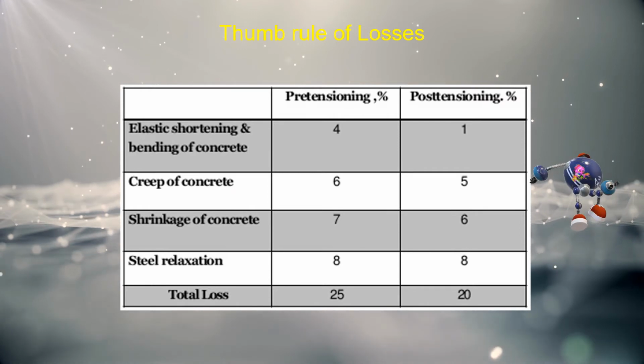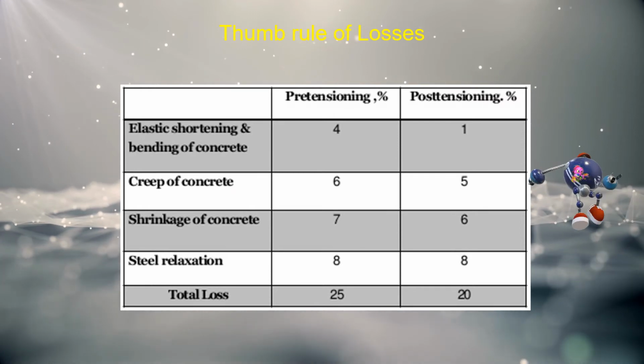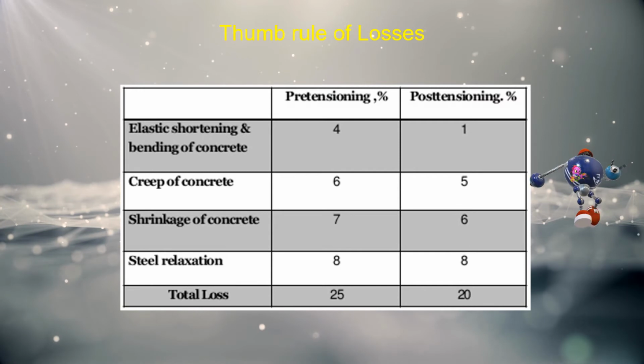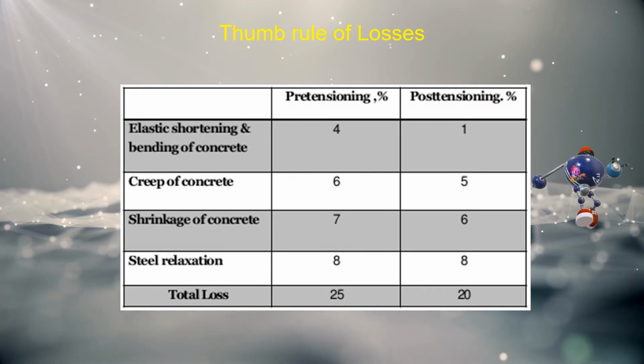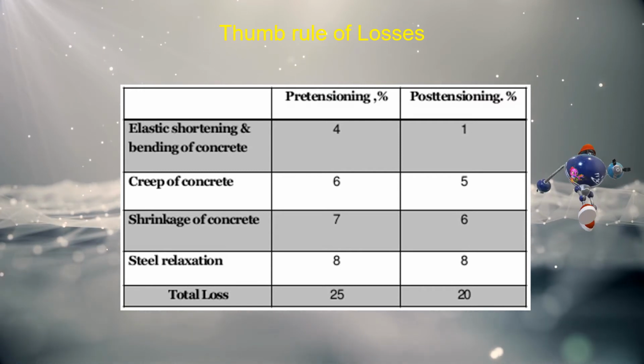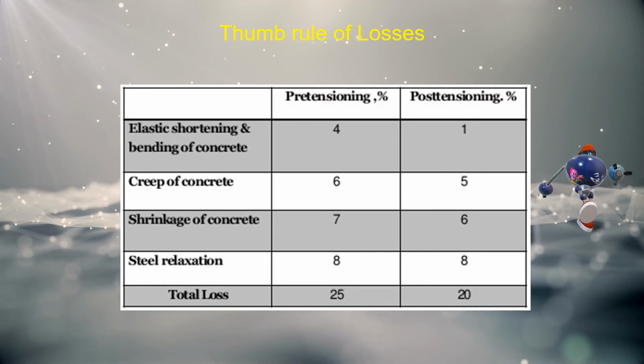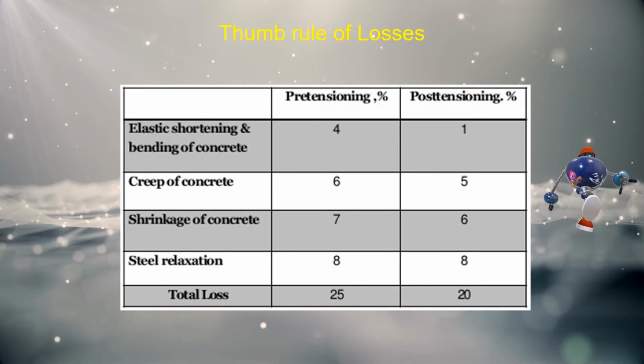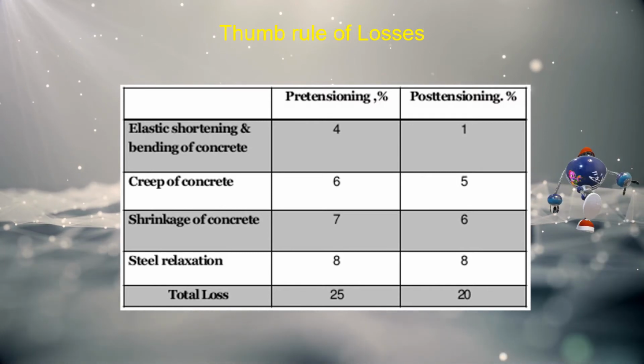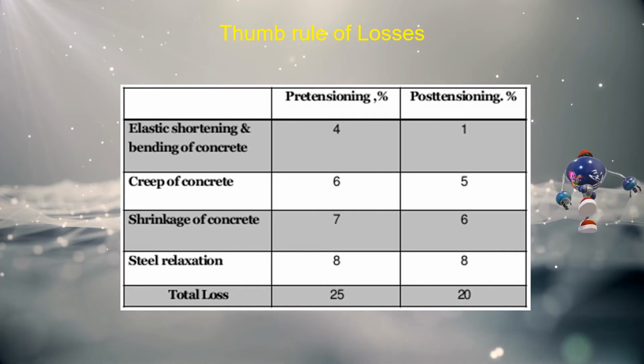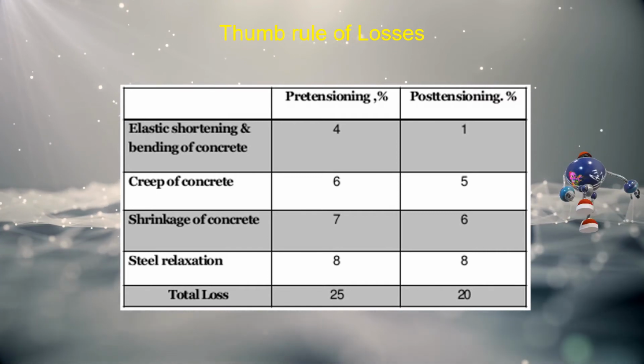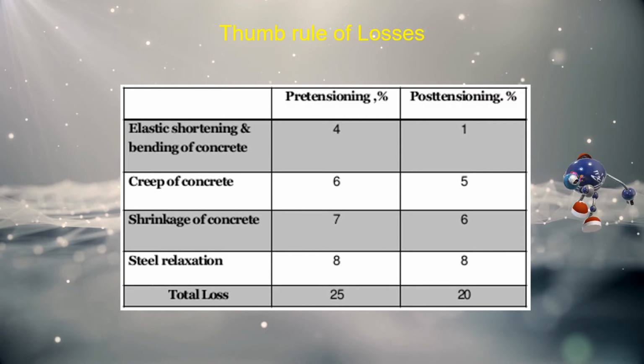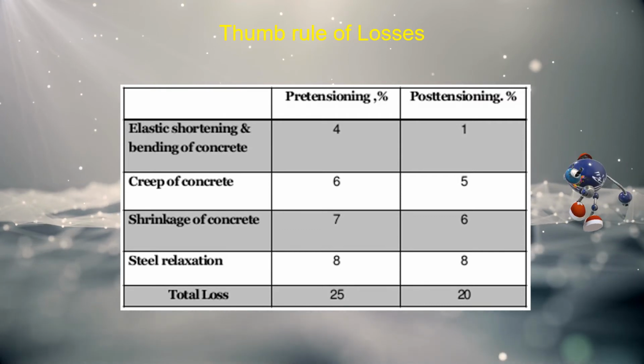The rule of thumb for losses. For average steel and concrete properties, the tabulated percentage may be taken as representative of the average losses. Overall, this shows that the pre-tensioning system loses more, at 25%, than the post-tensioning system, at 20%.